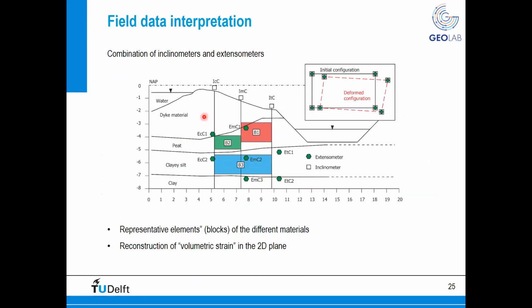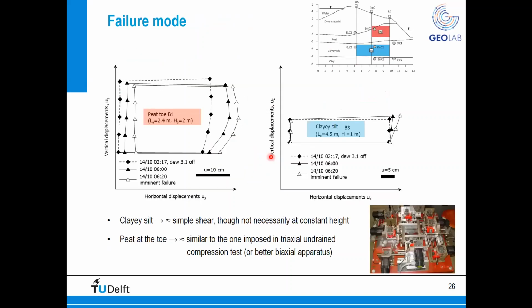Now, why did I mention that having information both on the lateral displacement and on the vertical displacement was important for us? As you remember, we were trying to test with this field stress test how different materials deform and behave in the field. So by combining the information from the inclinometers and the extensometers, we were able to define small blocks of material. So block B1, which is a block of peat, another block of peat below the crest of the dike, and one big block of clay. And by combining the horizontal displacement and the vertical displacement, we could reconstruct what we call volumetric strain in a 2D plane strain approach. And this is extremely important because this gave us the information to try to understand how these blocks of samples deform in the field.